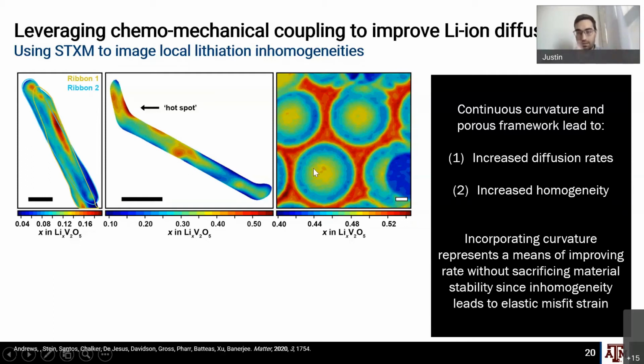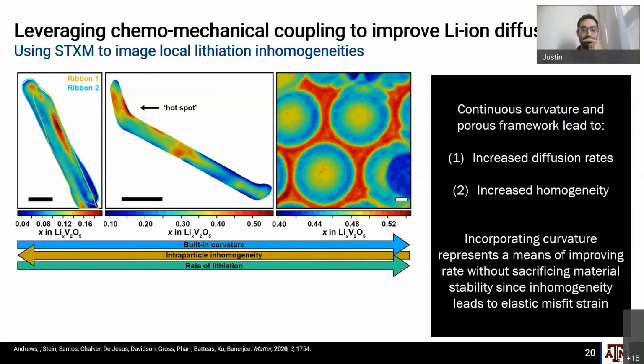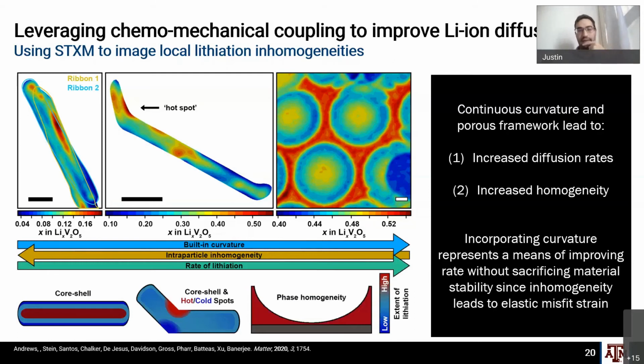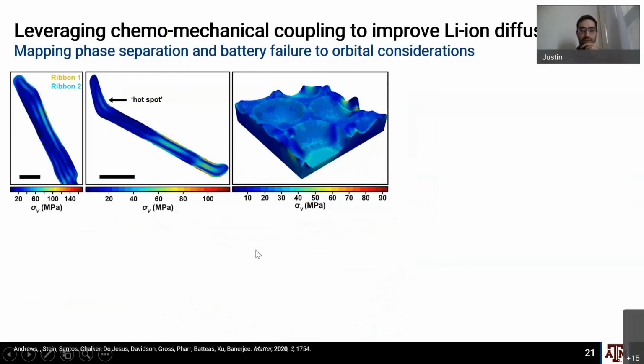So one way to mesh both worlds is to create continuous curvature, where we have that compressive strain in terms of the nanobowl morphology at all points, but it's continuous so that there's no significant inhomogeneity that arises as a function of rapid lithiation. So one schematic that shows this nicely is that in these straight V2O5 nanowires, we get this typical core-shell behavior. But we also get core-shell behavior in bent nanowires, where we get fast lithiation at compressive strain regions, and then we get slow lithiation on the opposite side, but that we get phase homogeneity and rapid lithiation in terms of the continuous curvature.